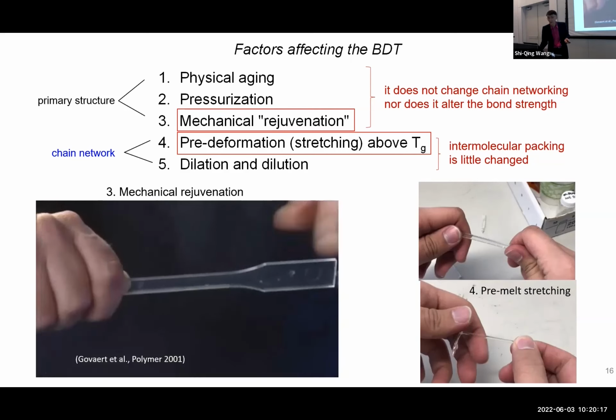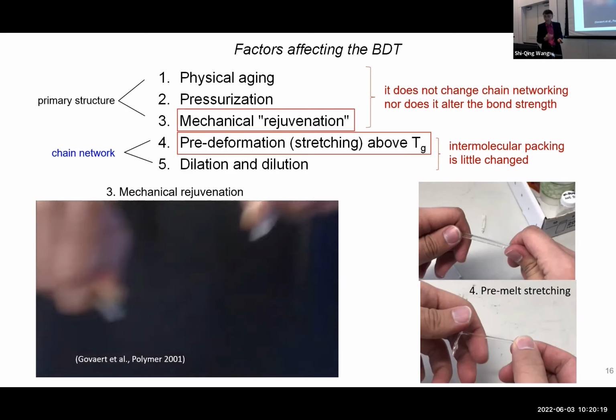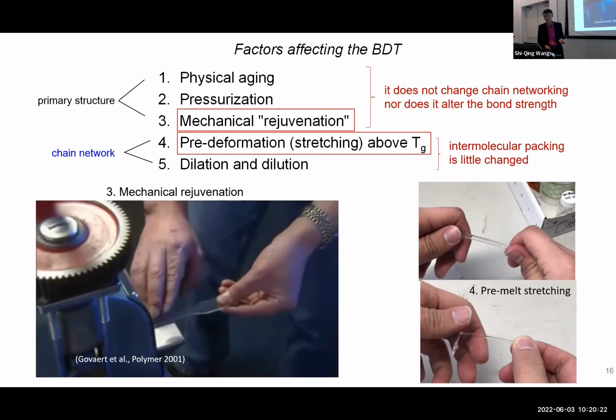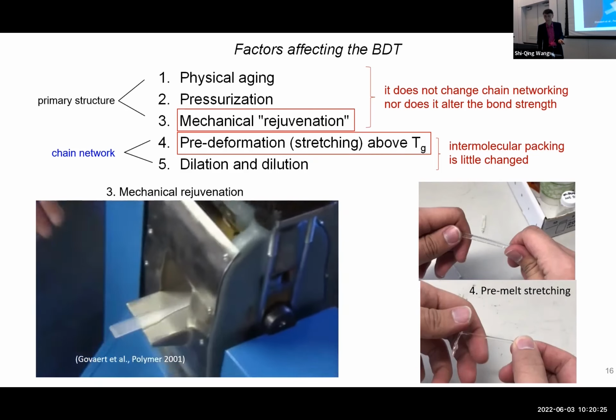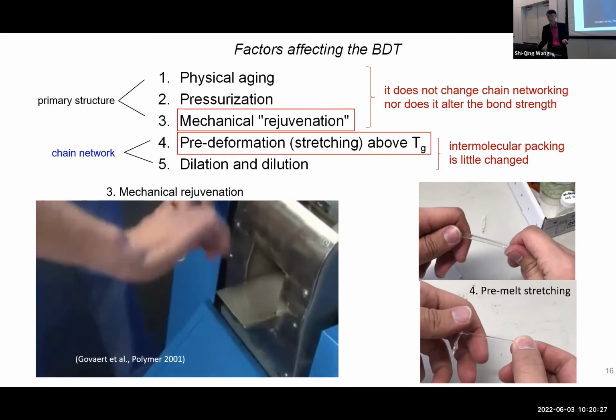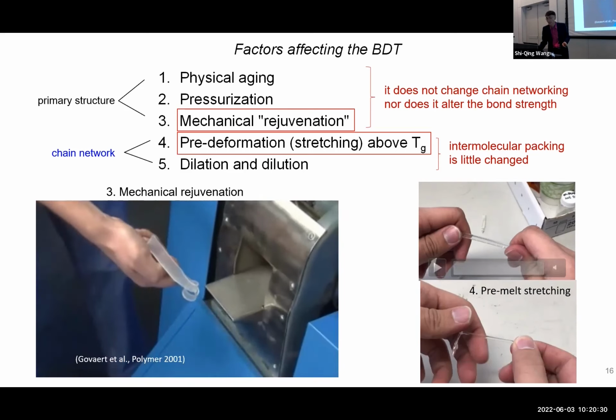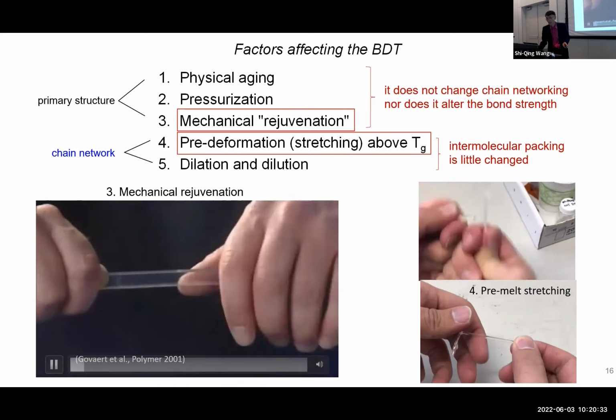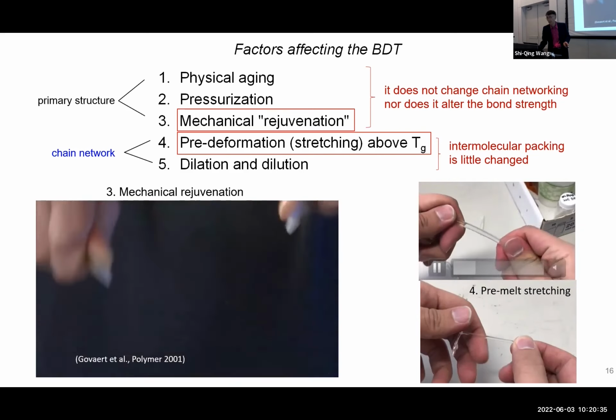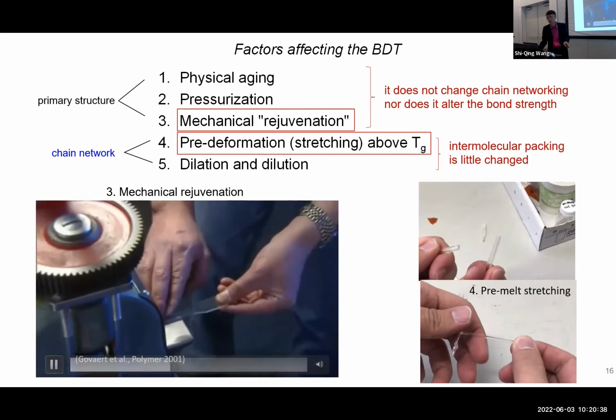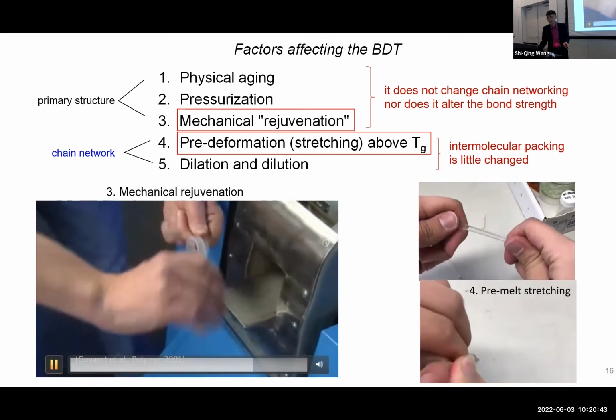One of the magician effects is the so-called rejuvenation. You pass your polymer through this cold two-roll mill, then this very brittle polymer turns ductile. So that's like no chemistry change, it turns ductile, right? So that's called rejuvenation, one of the effects. Secondly, if you have this polystyrene, it's typically brittle, but after melt stretching, it turns completely ductile. Okay, so these are the effects.